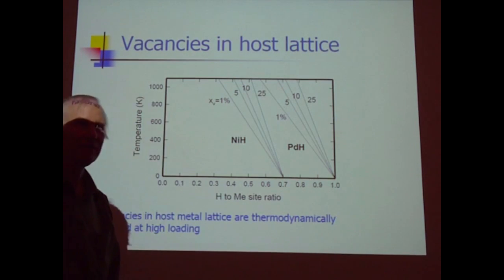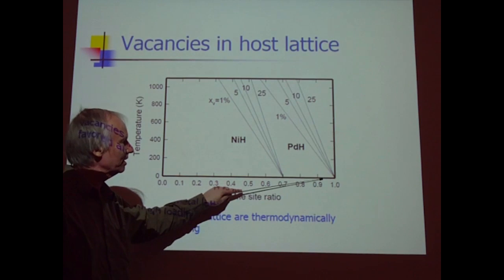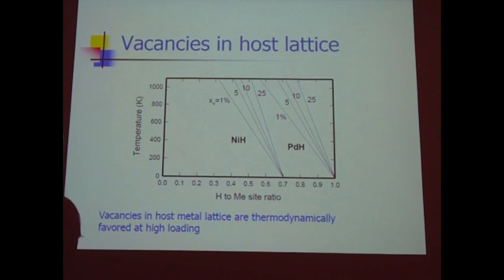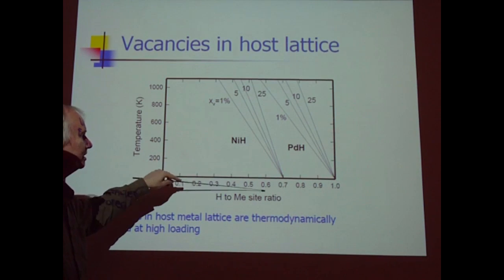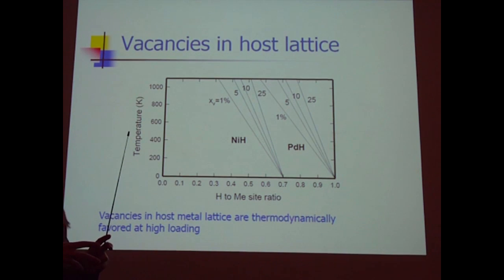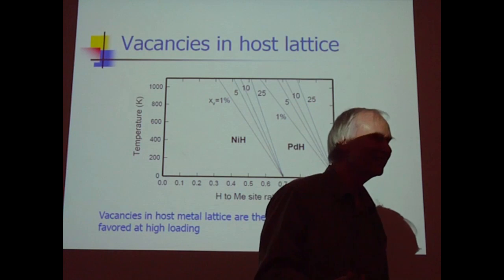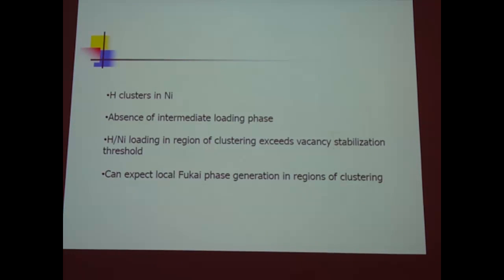Now, we were interested in vacancy formation, and we said in palladium deuteride, palladium hydride, you have to be loading at 0.95 to get your vacancy stabilized. Well, in nickel, you don't have to go up as high, and if clumping gives you 0.7, wherever you clump, you put hydrogen into nickel, it clumps, and it clumps at a local density sufficiently high to stabilize vacancy formation. Sure, we're definitely not in palladium anymore. This does not happen in palladium. So H clusters in nickel, there's not an intermediate loading phase observed in lattice constant measurements. And the loading that's observed is sufficiently high to exceed the vacancy stabilization threshold.